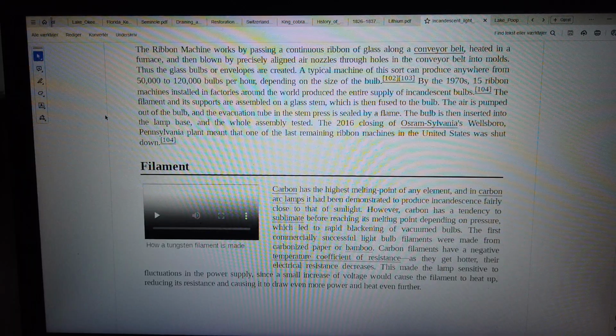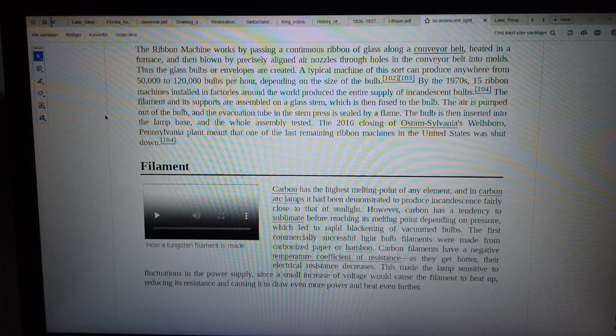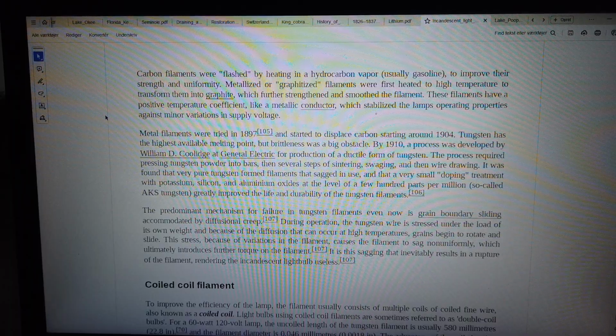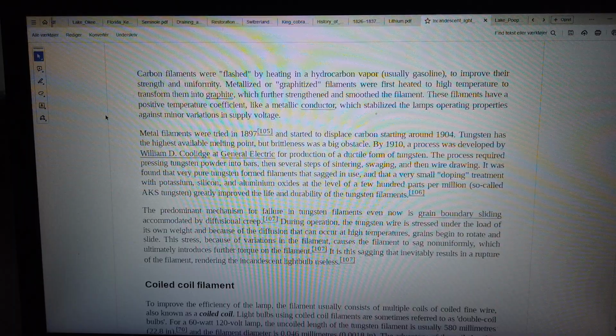Carbon filaments have a negative temperature coefficient of resistance. As they get hotter, electrical resistance decreases. This made the lamp sensitive to fluctuations in the power supply, since a small increase of voltage would cause the filament to heat up, reducing its resistance and causing it to draw even more power and heat even further. Carbon filaments were flashed by heating in a hydrocarbon vapor, usually gasoline, to improve their strength and uniformity.